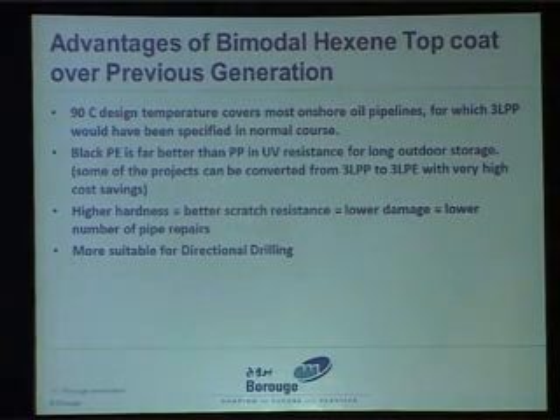Now, going by the book, for any pipeline project with 90 degrees centigrade design temperature, anybody will select 3-layer polypropylene today. But by using this hexene-based bimodal HDPE coating, one not only saves raw material cost compared to polypropylene, but it takes advantage of the very high UV stability of black polyethylene, which is a big weakness of 3-layer polypropylene coating. You cannot store 3LPP coated pipes outdoors for 2-3 years.